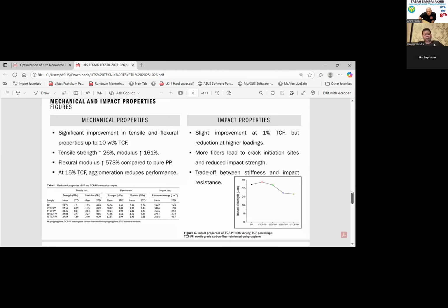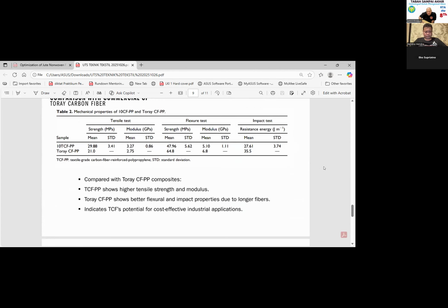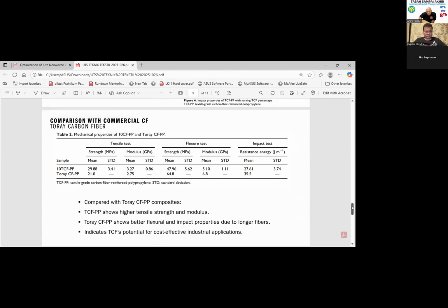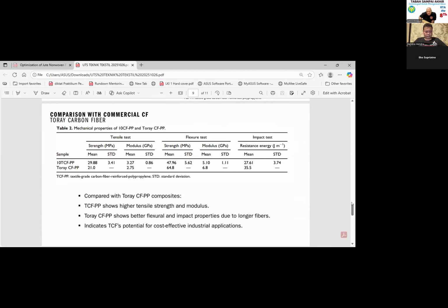This can be seen by comparing, Nadia, next slide, comparing with the commercial carbon fiber. We took the research that used the Toray carbon fiber. So let's see how they stack up against the commercial fiber here. The research compared their 10% TCF PP composite with the previously reported Toray carbon fiber PP composite that contains a similar amount of fiber. So here is what they found.